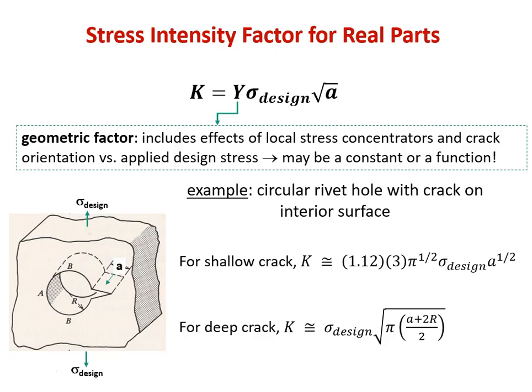But in this case, Y, rather than just being the square root of pi, is a general geometric factor, which includes the geometry of the part and the geometry of the crack relative to the loading direction. And it's different for every type, shape, size of crack. And in most cases, it will roll in any kind of geometric stress intensity factors like a smooth through hole or a section thickness or a fillet or a thread root.